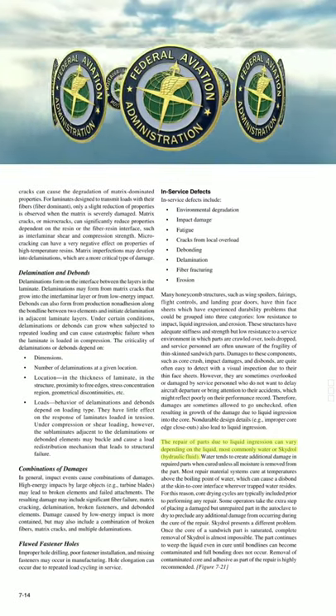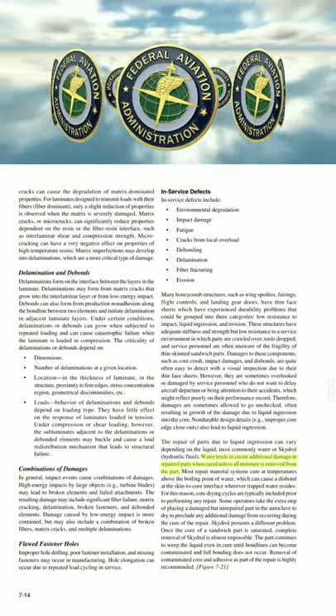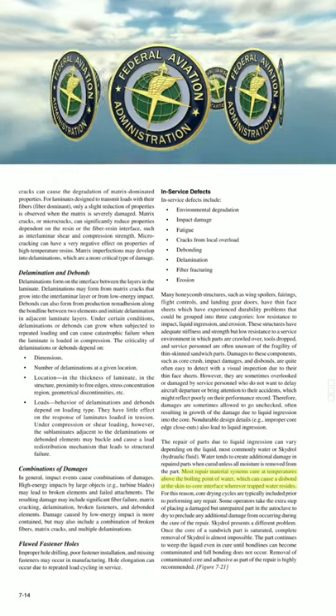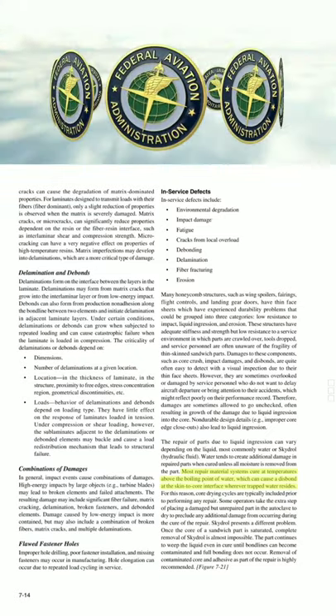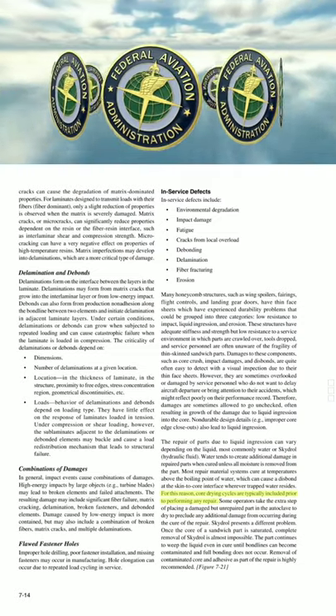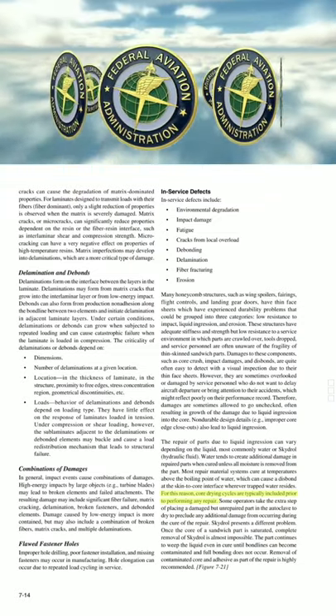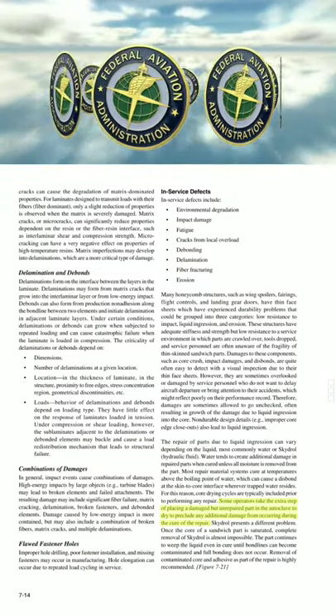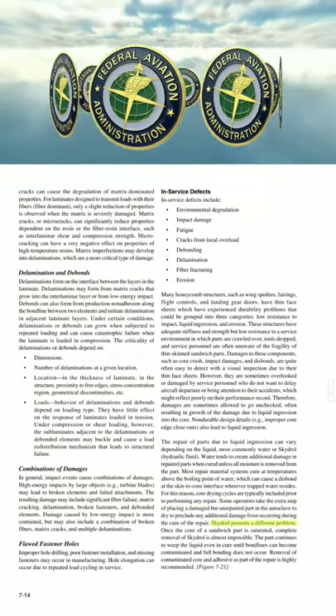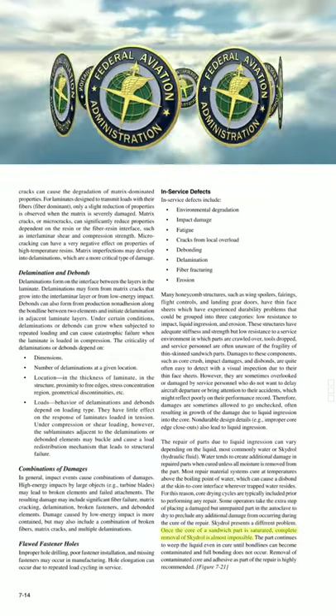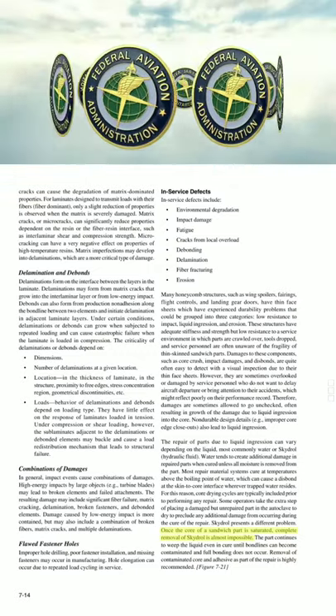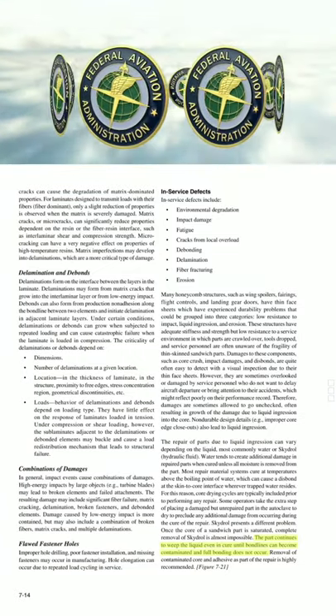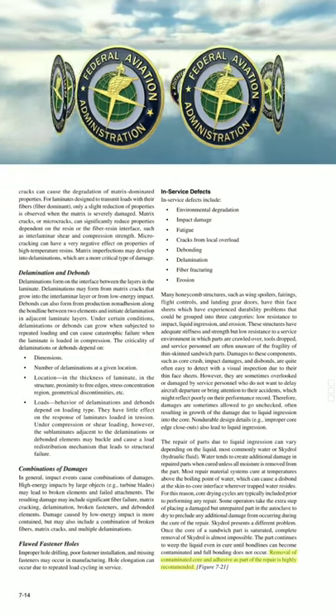Damages are sometimes overlooked by service personnel, often resulting in growth due to liquid ingression into the core. Non-durable design details such as improper core edge closeouts also lead to liquid ingression. Water tends to create additional damage in repaired parts when cured unless all moisture is removed, since most repair material systems cure above the boiling point of water, which can cause disbond at the skin-to-core interface. Core drying cycles are typically included prior to performing any repair. Skydrol (hydraulic fluid) presents a different problem — once the core is saturated, complete removal is almost impossible. The part continues to weep the liquid even after cure, contaminating bond lines. Removal of contaminated core and adhesive as part of the repair is highly recommended.